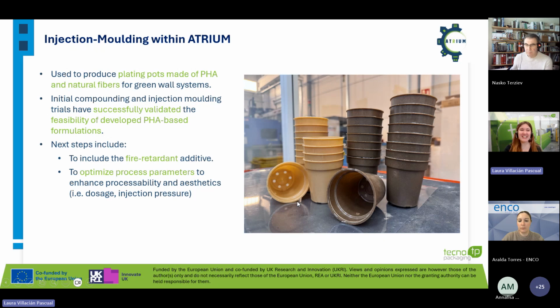So last but not least, what are we doing with the injection molding within ATRIUM? We have been using it to produce the planting pots made of PHA and natural fibers. You can see there some of the demonstrators that we have already achieved. The initial compounding and injection molding trials were successfully validated, which means that the PHA-based formulations fitted both the melt flow index that we needed for the injection molding, and the mechanical performance that was needed structurally for the planting pots.